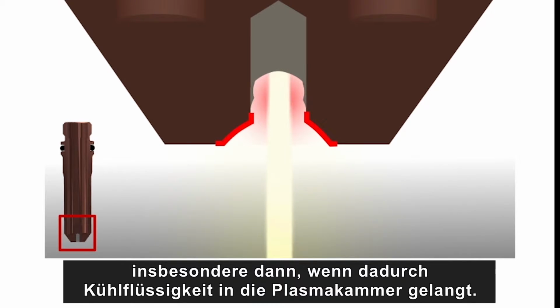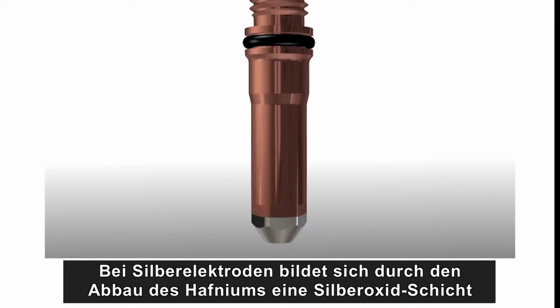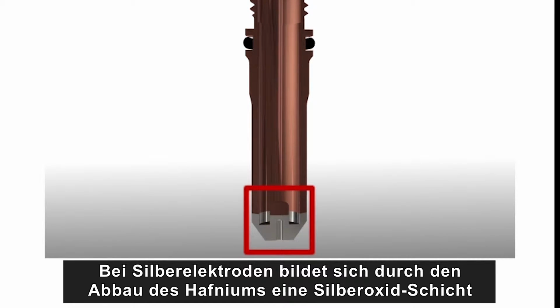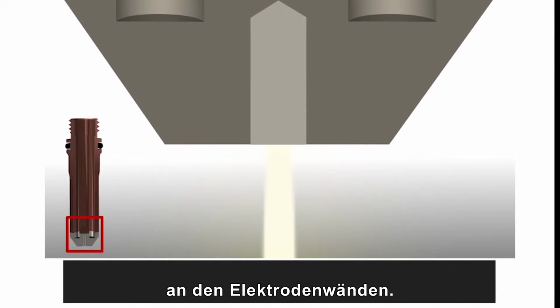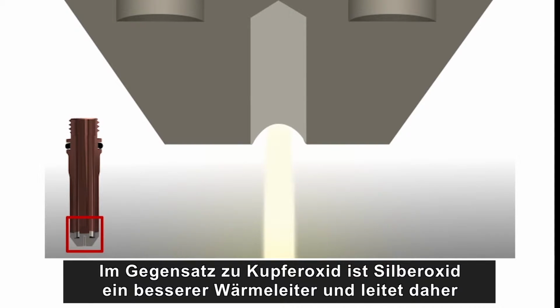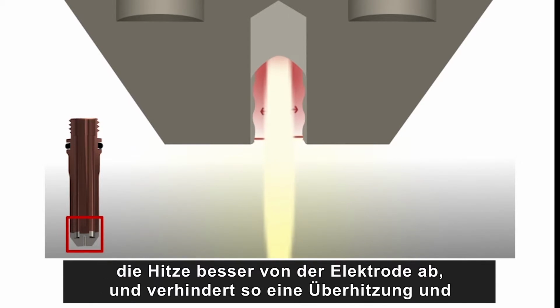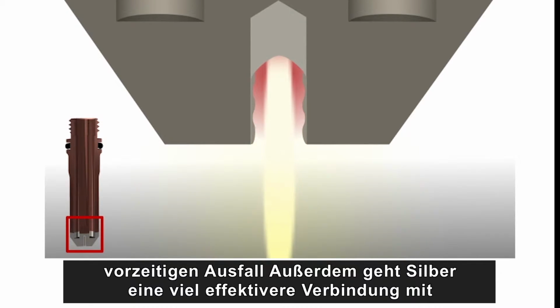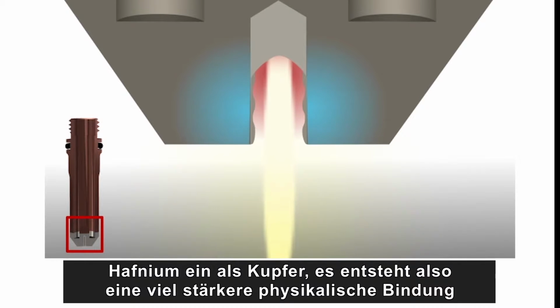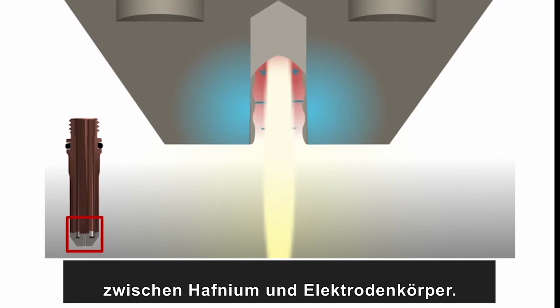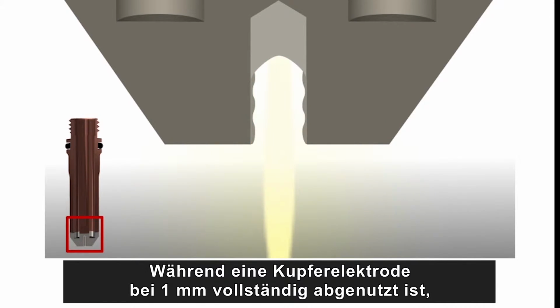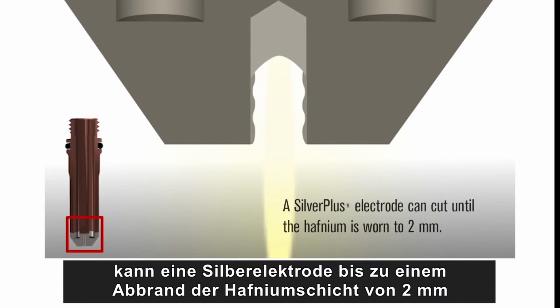The heat generated by the arc melts the copper, and if enough copper melts, catastrophic failure of the electrode and nozzle can result. With silver electrodes, a layer of silver oxide forms on the walls of the electrode as the hafnium wears. Unlike copper oxide, silver oxide works to remove heat from the electrode, preventing overheating and premature failure. Additionally, hafnium wets the silver much more effectively than it wets copper, providing a stronger physical bond between the hafnium and the electrode body. While a copper electrode is fully worn at 1 millimeter, a silver electrode can cut until the hafnium is worn to 2 millimeters while still maintaining good cut quality.